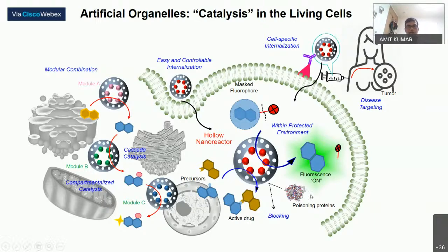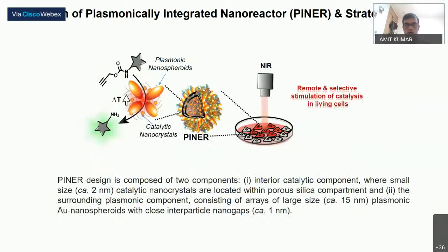So in the very first design of such a nanoreactor, we thought to combine catalytic and plasmonic components. We chose a design where the catalytic nanocrystals, which are very small in size, are embedded inside the nanoreactor, and the periphery has the plasmonic function. In such a setup, the plasmonic and the catalytic functionalities are closely interfaced. If you shine light on such a system, the plasmonic corona will be activated and it will transfer the energy to the catalytic sites, and hence it will promote the chemical reaction. So this was the idea.